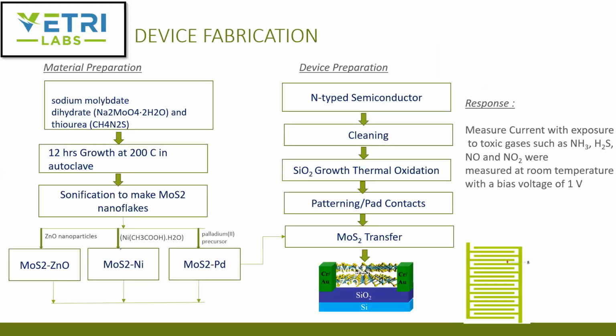Going to the next slide. Device fabrication. In terms of material preparation, it was a solvent wet chemistry based process. The hydrothermal process is also called solvothermal if it doesn't include water. This included water. The starting point precursors were sodium molybdate dihydrate and thiourea. After 12 hours at 200 C in an autoclave, they make these moly sulfide flakes or particles, and then they sonicate it to suspend them out of the solution.